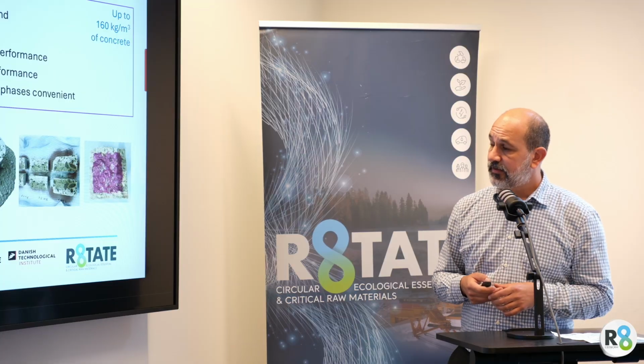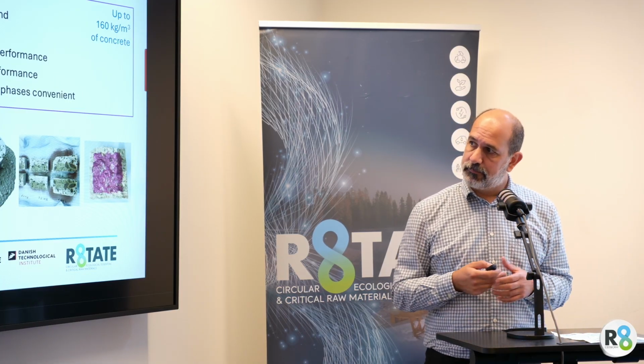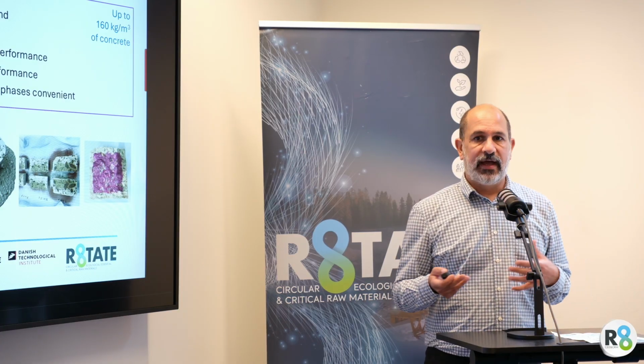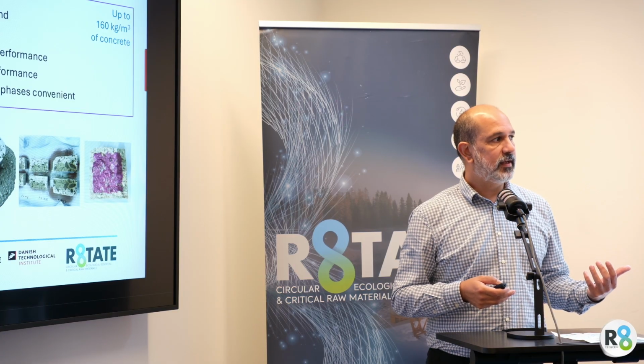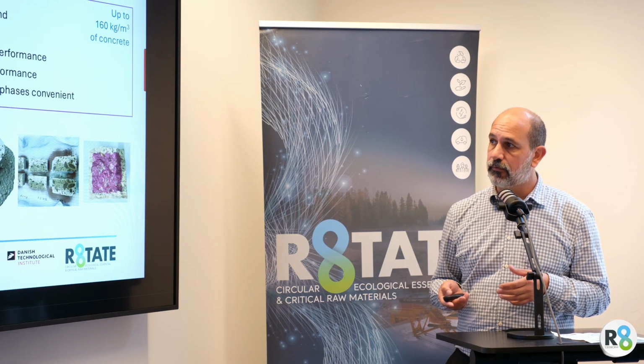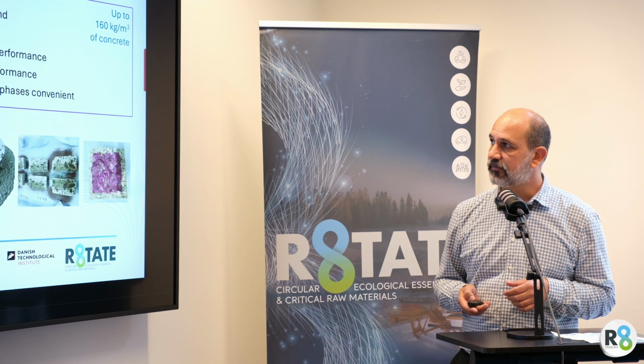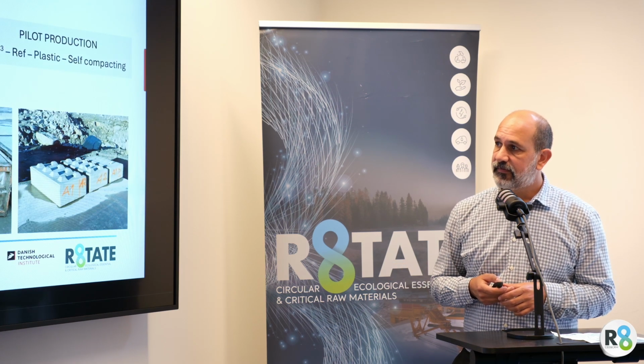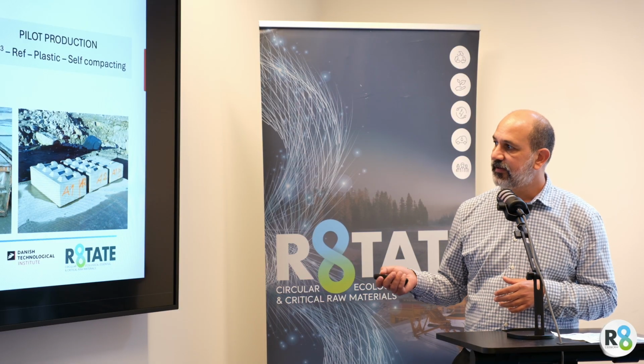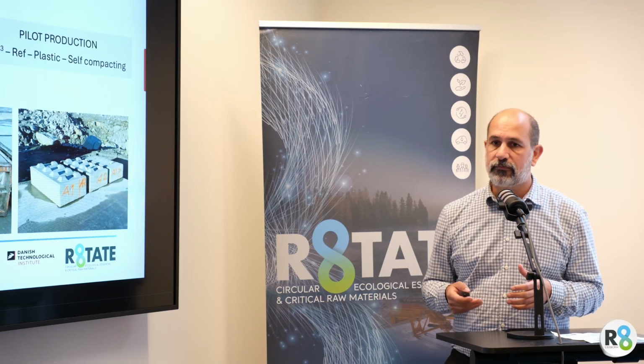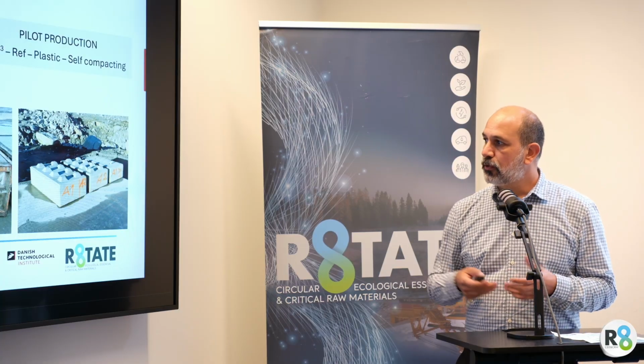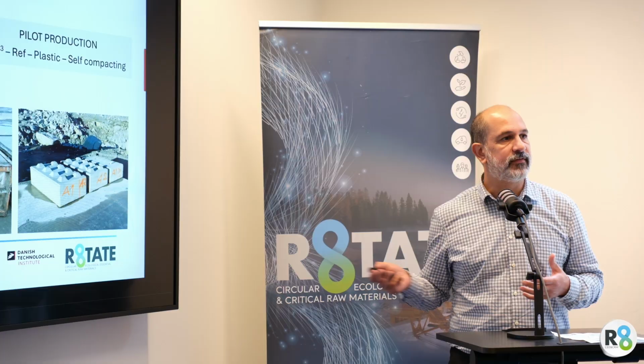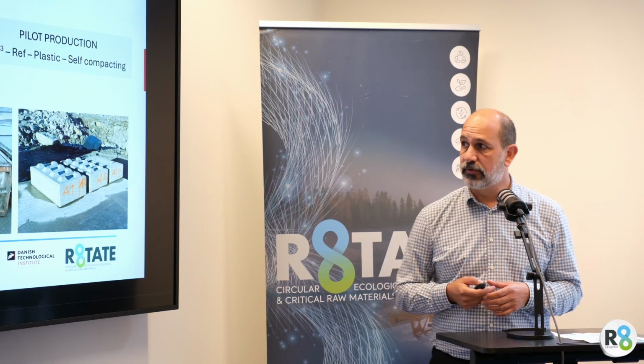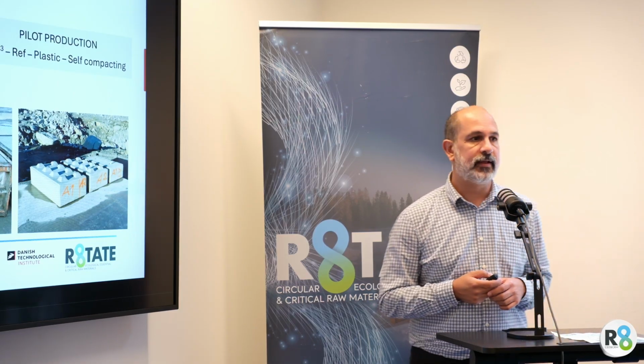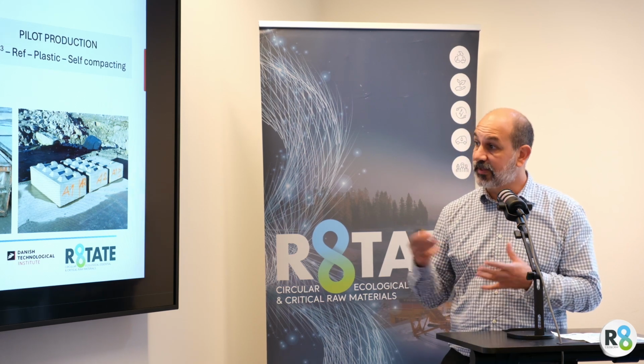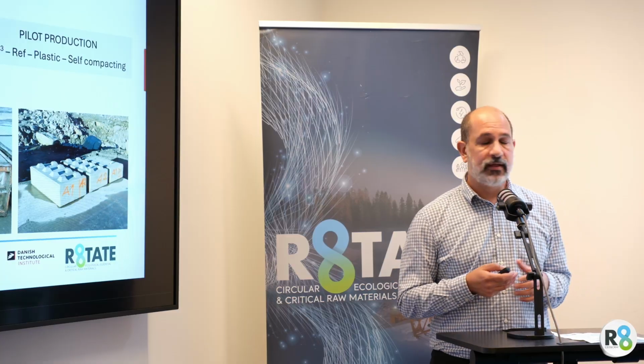But we succeeded. Main conclusion for this is that to improve the competitiveness of this filler, some additional methods to try to reduce the clay content would be convenient. So we would have a material performing more similarly to other competitors in the market. With these concrete recipes, we went to Velde, and they produce these Lego blocks that you see here in the picture that have been exposed for more than a year at the moment. And they show no signs of any different performance than the concrete recipes that they are normally using. So this is a successful case that we could prove the filler can be used from a technical point of view in these concrete mixes without any impact on performance.